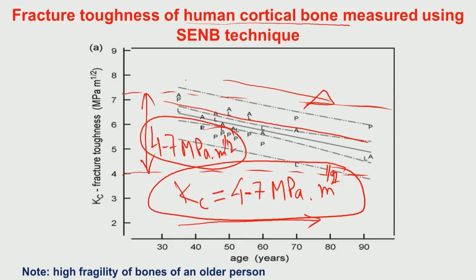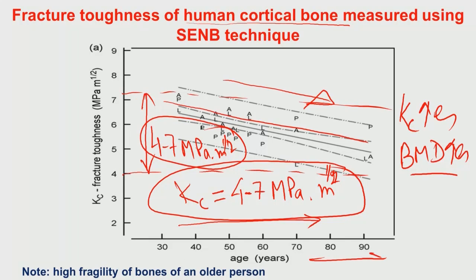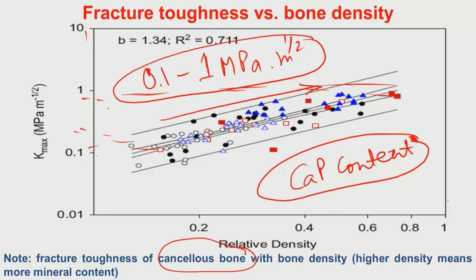And also they show bone mineral density dependent fracture resistance properties. In both the cases, you can see in the cortical bone also that Kc increases as the bone mineral density increases. Because if you look at the age going to the right hand side, if you plot the bone mineral density, that should go on the left hand side. So, larger the bone mineral density, more is the fracture toughness. And here again, you can see that more is the bone mineral density, more is the fracture toughness. This is also true for cancellous bone.